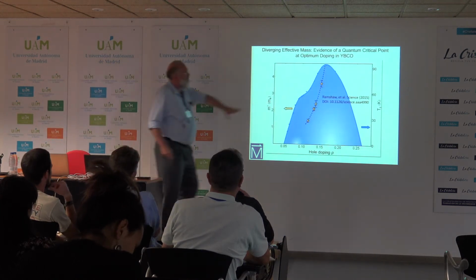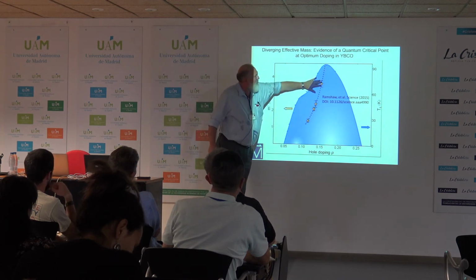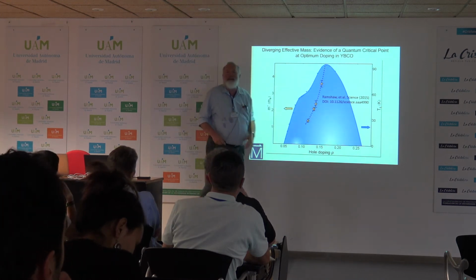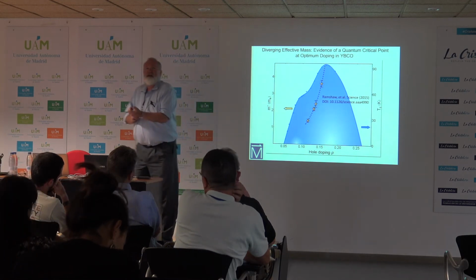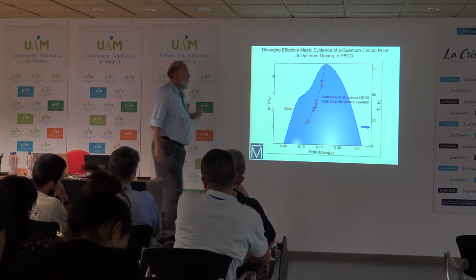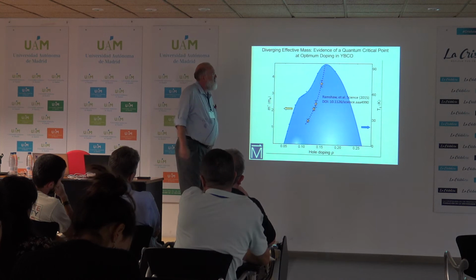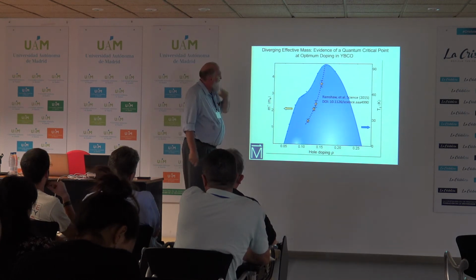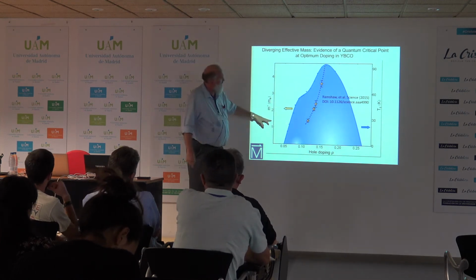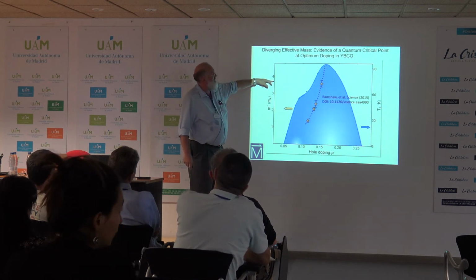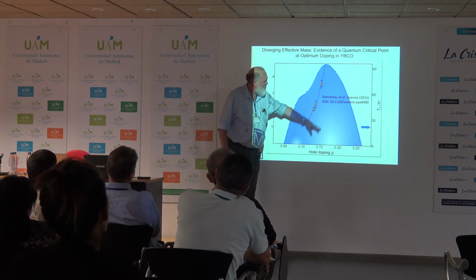But when they measure the temperature dependence of those quantum oscillations, the speed with which they decay gives you direct information on the mass of the quasiparticles. And this is a single pocket system, so it's a very simple analysis. And this mass goes from about 1.3 up to about 3.7 over a very limited range of doping.